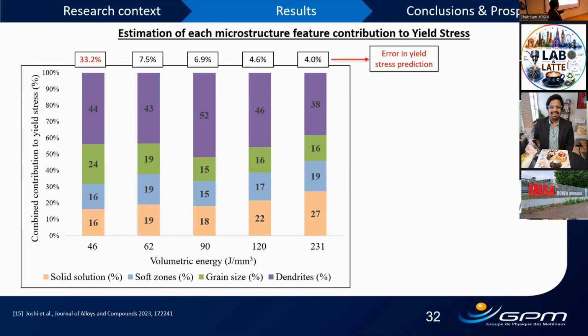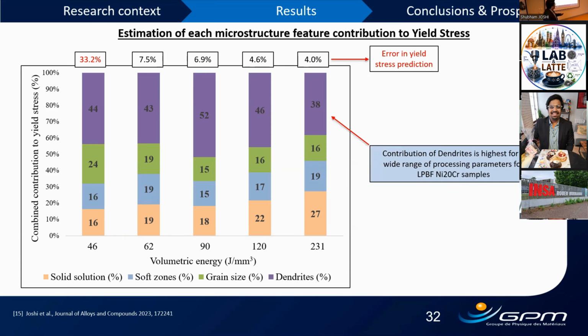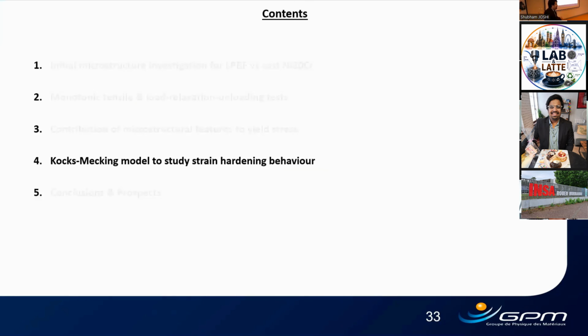Unfortunately, for 46 joules per millimeter cube, the prediction was way off. We were 33% higher. But for other samples, the error percentage is, I guess, for me at least, quite acceptable. So again, just to conclude, for all the LPBF samples, we can consider that dendrites are the most influential parameter. So basically with that, we answered the first question. For yield stress, dendrites is the solution. You know a guy, dendrites is your guy for yield stress.